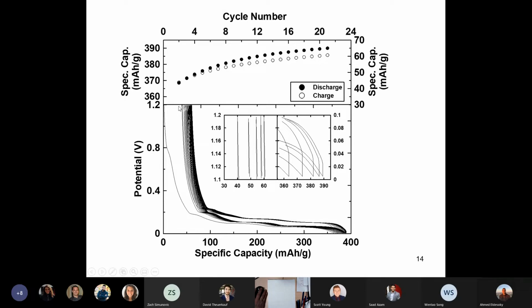So what's very interesting to do is just plot the endpoint of the discharge, or the endpoint of the lithiation here, versus the cycle count. So that's what's happening here with the solid symbols up above. Okay, so it starts around 368 milliamp hours per gram. And as you can see, as you cycle more and more, it approaches 400. So that's what the solid lines are doing. Okay, and this increase in capacity is all lithium that's going into the ever thickening SEI.